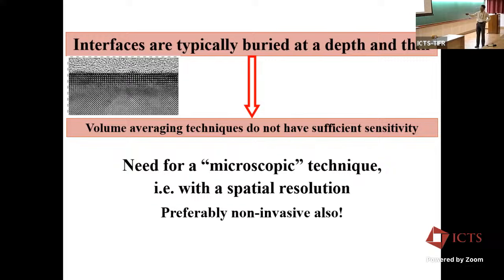You can say, look, this TEM is perfect. I can see the interface. I can study its interface and atomic structure. And knowing the atomic structure, I can work out what the electronic structure is all about. But this is a very invasive manner. What do I mean by that? You had a system, and then you had to cut open here so that you expose a surface, and then you can do the cross-sectional TEM to look at the interface. And that means you introduce a new interface, the vacuum, to these two A and B material interface, and that can change the property completely.